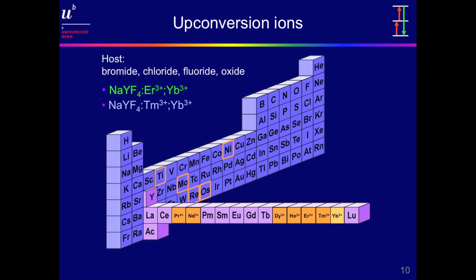Ytterbium often serves as a sensitizer, an upconversion sensitizer, because it has a relatively strong absorption around 1 micron. We also found upconversion in some transition metal ions: nickel 2+, titanium 2+, molybdenum 3+, rhenium and osmium 4+ in suitable lattices. Please notice the green and the blue materials on the upper left. Sodium yttrium fluoride doped with ytterbium erbium or ytterbium thulium. These materials had been known since the early upconversion work in the 1960s, and they were known to be efficient upconverters, but nobody knew why.